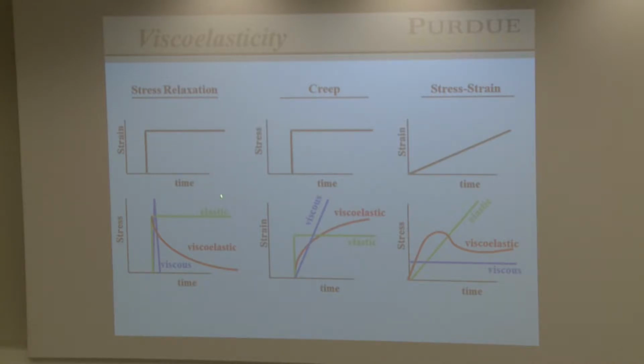Now we can invert the experiment. Over here, instead of applying a step change in strain, we can apply a step change in stress. In that case, the elastic material responds again with a step change. A viscous material now, because the stress is constant here, will have a linearly increasing strain, or if we took the derivative of that, a strain rate. And the proportionality constant would be called the viscosity. A viscoelastic material doesn't look like that at all. It has this somewhat exponential-like growth behavior.